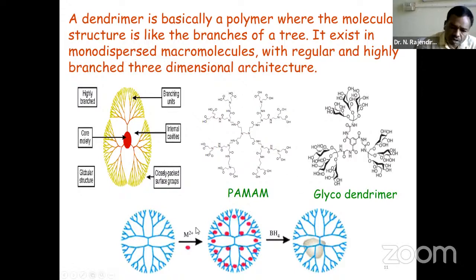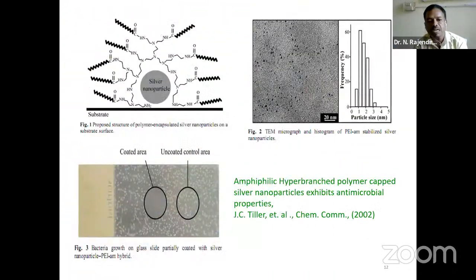So when you add the metal salts initially, because of the attraction between the functional groups and the metal salts, they are embedded on the topologies, and once you add the sodium borohydride, the metal salts are reduced into metal nanoparticles. This is another example, polyethylene imine. This is one of the hyperbranched polymers we can use as a stabilizing agent for the stabilization of metal nanoparticles. Here they used it for the encapsulation of silver nanoparticles using polyethylene imine, and after the reduction they confirmed by transmission electron microscope as well as DLS.